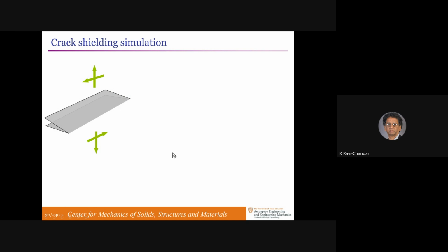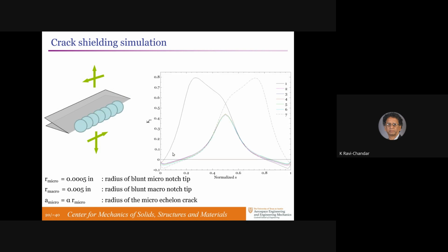It's easy to understand the coarsening with a very simple simulation. Suppose you think there's a system of daughter cracks, periodically spaced, subjected to a mode 1+3 loading in the far field. They create a stress intensity along the curved crack front that allows them to grow. That stress intensity factor, mode 1, is given by these lines. Ignore these two from the endpoints, which have edge effects that we didn't take care of. If you suddenly allow one of these cracks to expand and redo the calculation of the stress intensity factors for these cracks, note that all of the cracks experience nearly the same stress intensity when they're uniform.